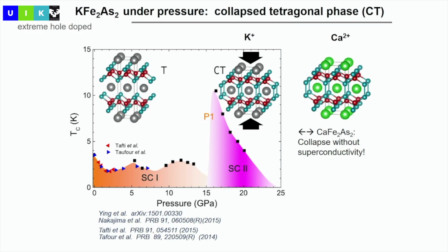Now, what we know that happens at these pressures is that there is a volume collapse in the system. So what happens is when you press the system, you see here, these are arsenic atoms, and basically you have pz orbitals that are facing like that. If you press the system, there is a critical pressure where these pz orbitals really overlap, so you have a bonding anti-bonding type of response, and therefore the system goes into a lower energy state if it just compresses along the z direction, and this is the collapsed phase.